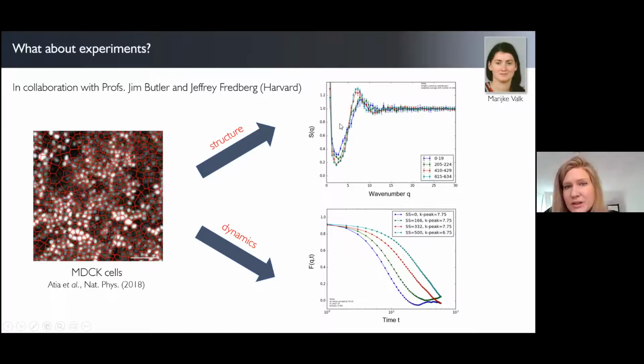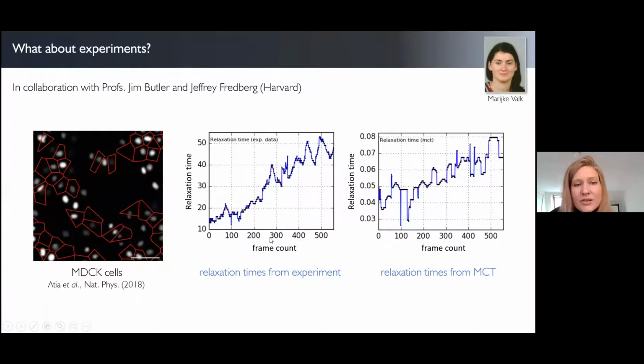So these are the static structure factors and the intermediate scattering functions from experiment. And then we also applied mode coupling theory again to see if, from only the static structure factor, we can predict the slowdown in dynamics. And so here you see the results.